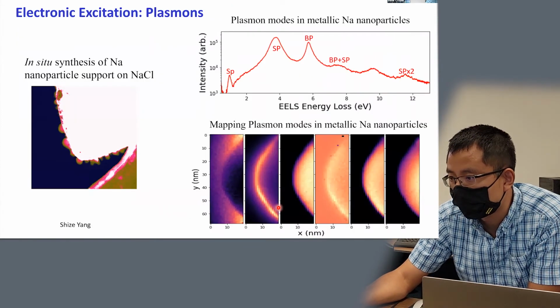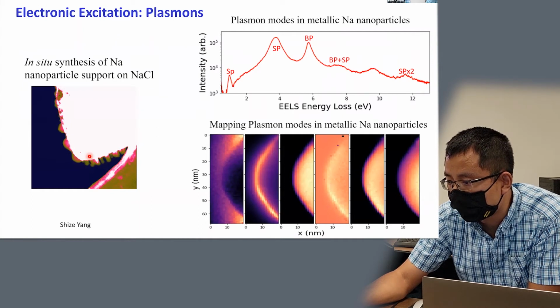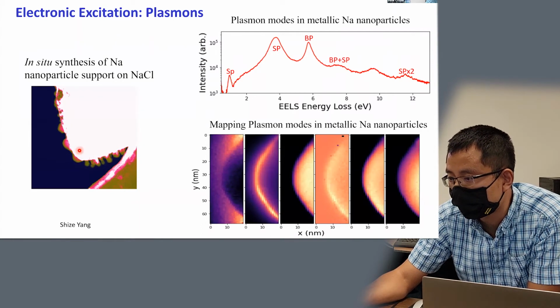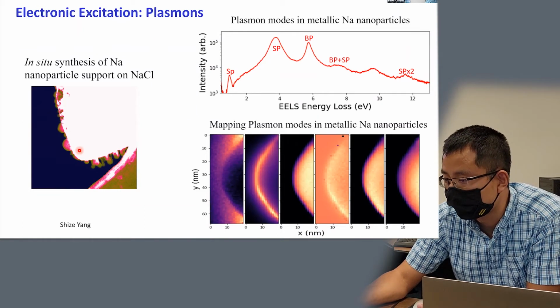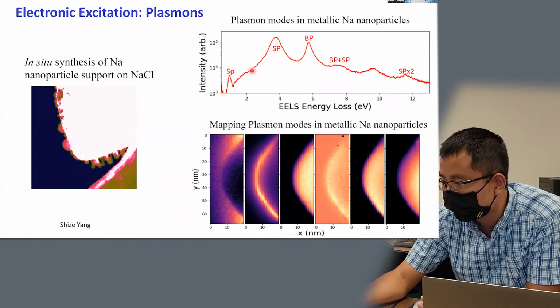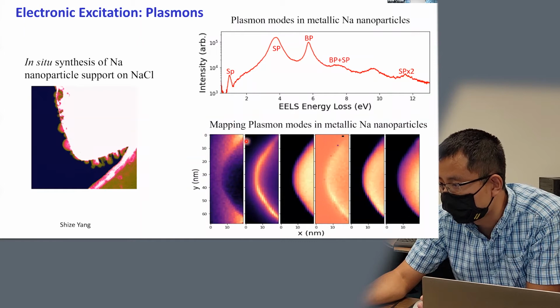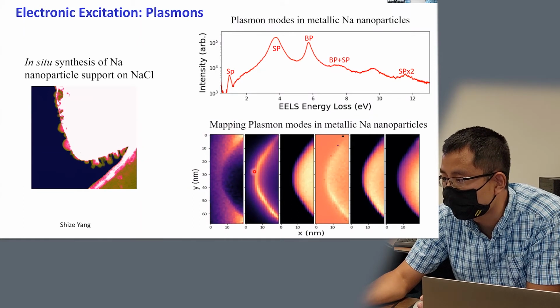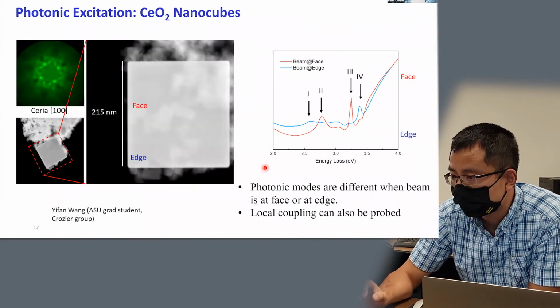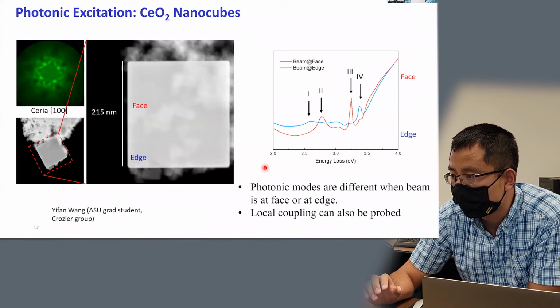Then another example is that we can probe plasmons. On the left is a movie showing that we can use the electron beam to produce sodium nanoparticles supported on a sodium chloride cube. And then we can use EELS mapping to probe the spatial distribution of different plasmon modes in real space. Here is another example, where we can measure the photonic modes in CeO2 nanocubes.